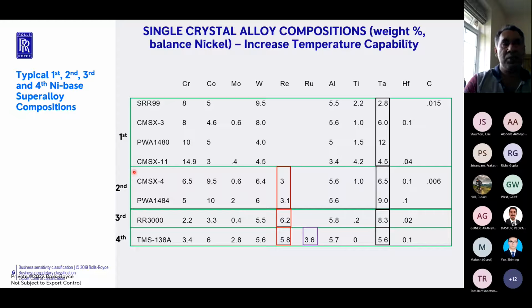So if you look at the evolution of single crystal alloys from the point of view of temperature capability of substrate materials, it spans 4 generations. The first generation, roughly, you would say in the early 80s. The fourth generation, pretty much the late 2010s, it's around after 2010. So when you go from the polycrystalline alloys to the first generation single crystal alloys, the main difference is in the addition of a refractory alloying element like tantalum. And these first generation nickel based alloys have got tantalum added to them.